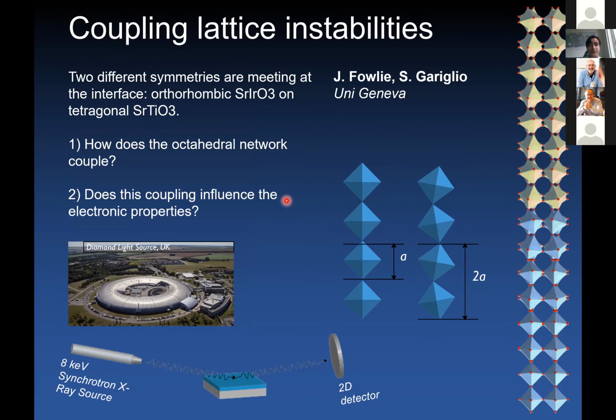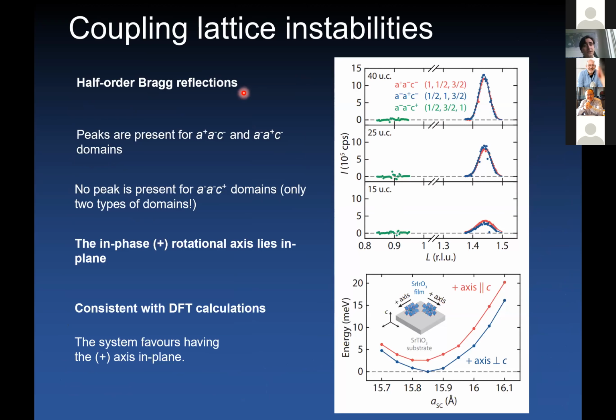We wanted to really understand how this octahedral network couples across the interface, and how we can rationalize the influence that they have on the electronic properties. In order to address these questions, we went to Diamond Light Source, and we teamed up with the group of Jean-Marc Triscone in Geneva, especially with the help of Jennifer Fowlie and Stefano Gariglio. We went to measure essentially the doubling of the unit cell of these materials that is triggered by this pattern of oxygen rotation below the phase transition. When you go from a straight octahedral network to a pattern of tilts of the octahedral network, you immediately see that your unit cell is being doubled along a certain direction. Therefore, you want to measure half-order Bragg peaks that will directly see these rotations in place.